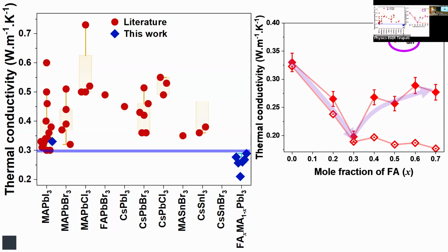But what makes it come down in the beginning? FA size is slightly larger than MA. In this limit, with FA, the average volume is increasing, and that allows the MA to rotate even faster. We had not known about this, but we had already published 4 or 5 years before from small angle neutron scattering, showing that MA actually begins to rotate faster in the small doping of FA limit. So it indeed rotates faster as the volume increases, and that allows it to bring down, but the volume increase does not compensate for the decrease of MA ions. So the number of dipoles is going down, and so it begins to go up.